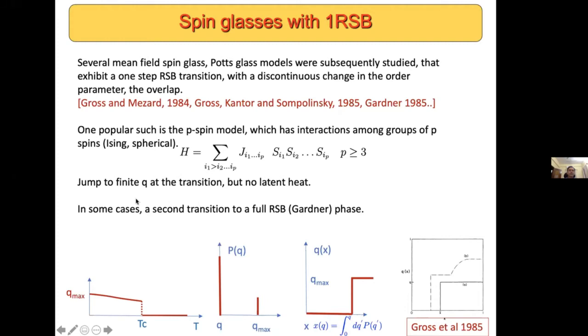And the overlap distribution function basically below the transition develops a mode at a finite value of Q, in addition to the one at 0, which is what one has in the paramagnetic phase. And if one looks at this quantity x, which is the integral of P of Q with respect to Q, this shows this step-like behavior.